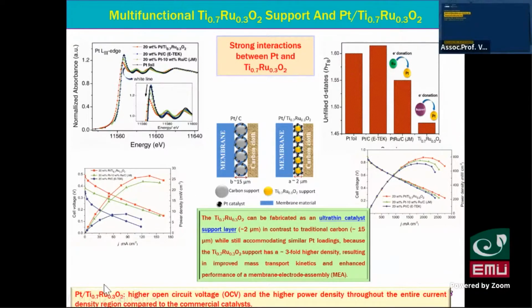After that, we used fuel cell tests to show the power density of our catalyst compared to commercial catalysts, Pt on carbon and Pt-ruthenium on carbon. These are very famous commercial catalysts; our catalyst, shown in red, has power density higher than the commercial ones. The blue line is Pt on carbon, and the green line is Pt-ruthenium on carbon.